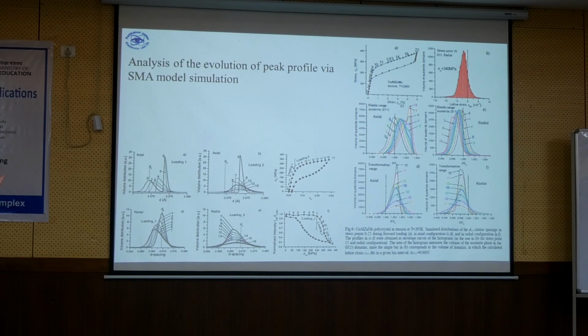In this case, there are no dislocations. But we see the same phenomena, but no dislocation. So the question would be, what is the reason for the peak broadening over here? Imagine that this profile comes from, for example, 1000 grains. If in each grain there is the same stress, the peak will be narrow. If in each grain the stress is different, the peak width will grow. So you have a different mechanism for peak broadening. Forget about dislocation. Now the mechanism is the distribution of stresses within these families of grains.